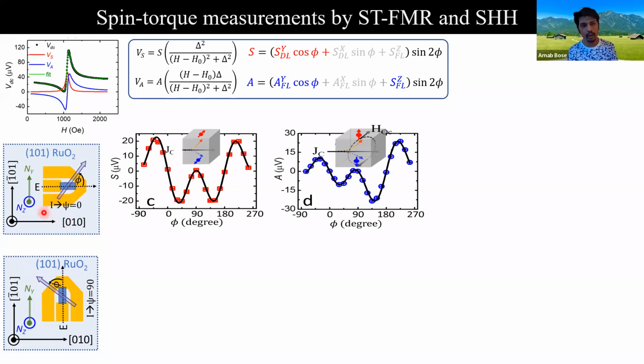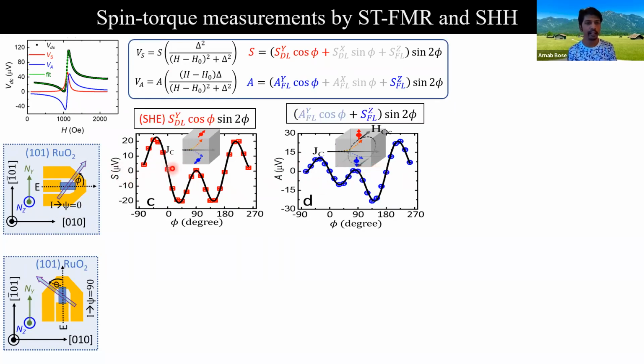Here, I have shown that when we run current along this direction, psi equal to 0, there is a clear difference in the symmetric and the antisymmetric components. The symmetric component has cos phi, sin 2 phi angular dependence that originates from the regular spin Hall effect. However, for the antisymmetric component, the difference is due to this extra term, that is sin 2 phi. That clearly suggests that we have out of plane spins generating from the in-plane current in this direction. And on top of that, we have regular cos phi angular dependence that leads to this angular dependence in the antisymmetric component.